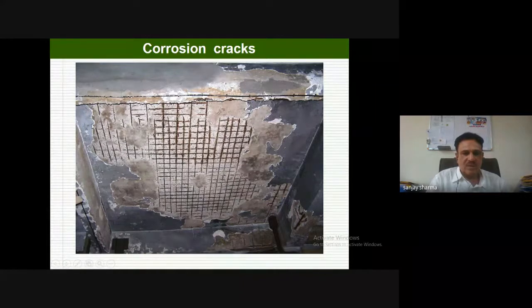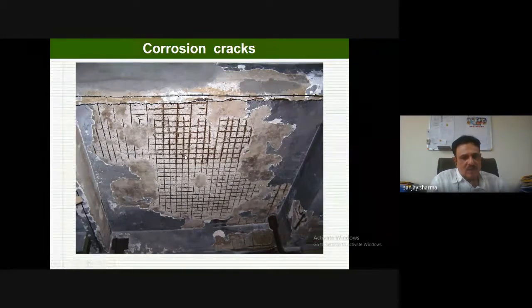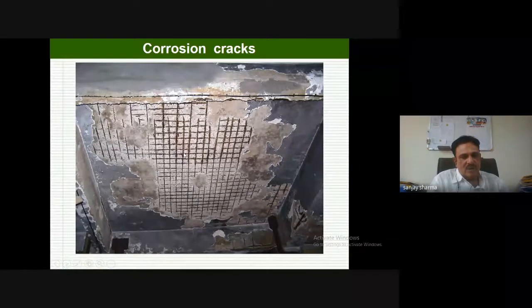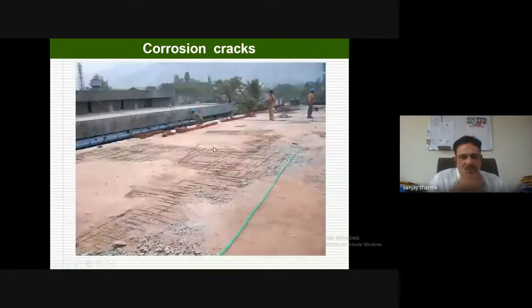You can see that the whole slab cover concrete has come down, and the area of section has almost reduced to zero. So basically, we need to know the extent of corrosion. For that, we have corrosion tests available, the corrosion meter or resistivity meter. With the help of this corrosion analysis, you can find out the extent of corrosion, whether your bars have reduced by almost 100%, or maybe 50%, or maybe 30%. With the values obtained from the corrosion test, we can assess this.